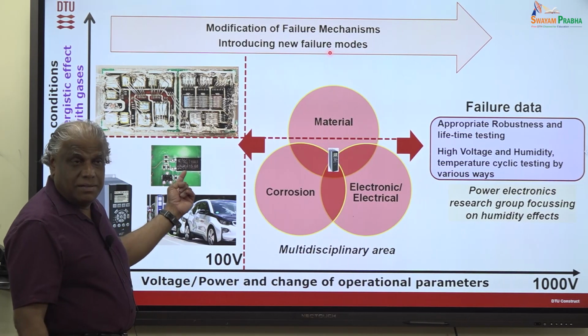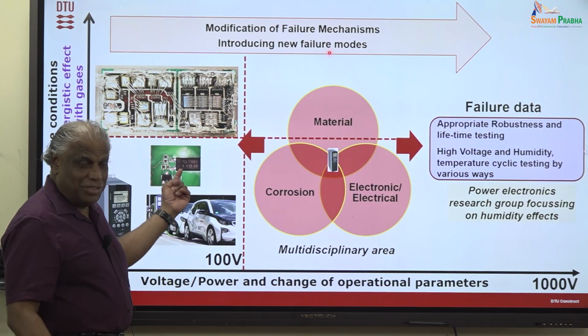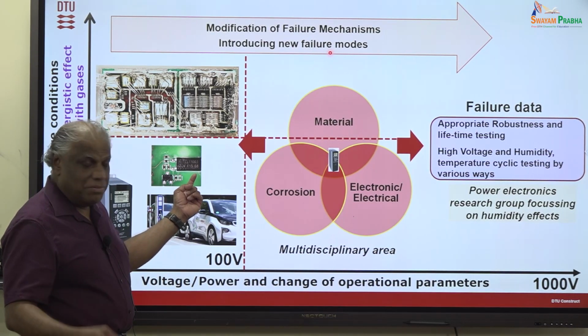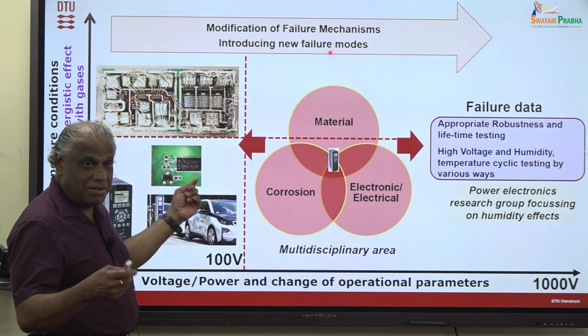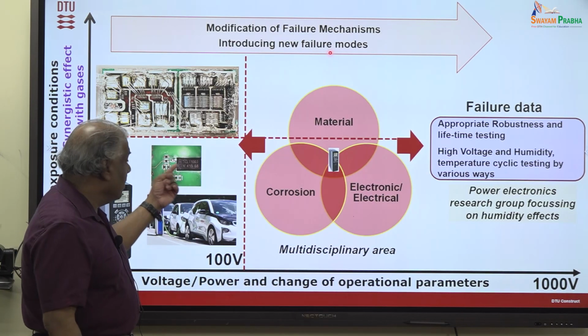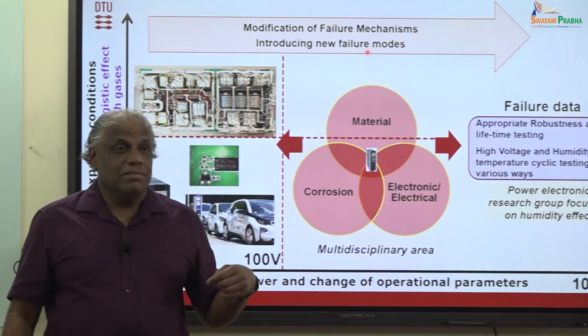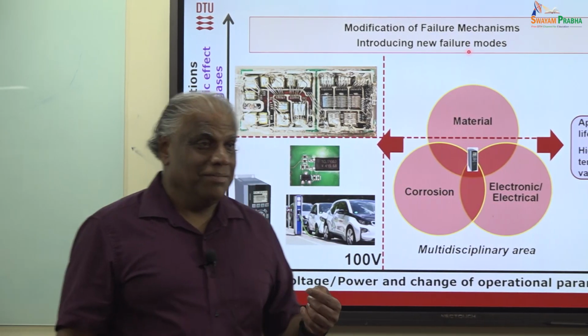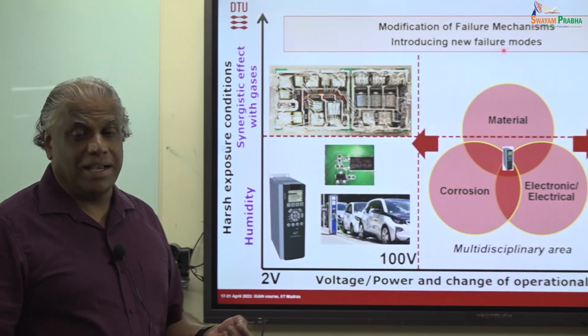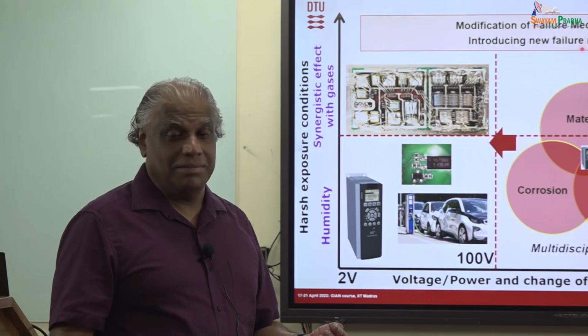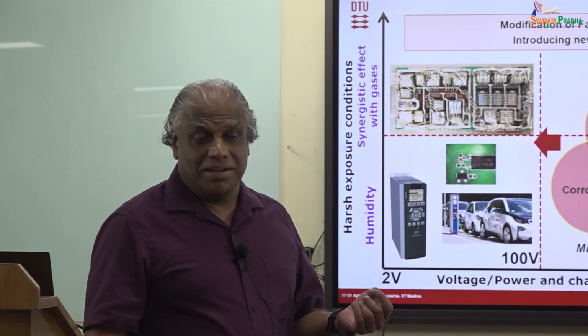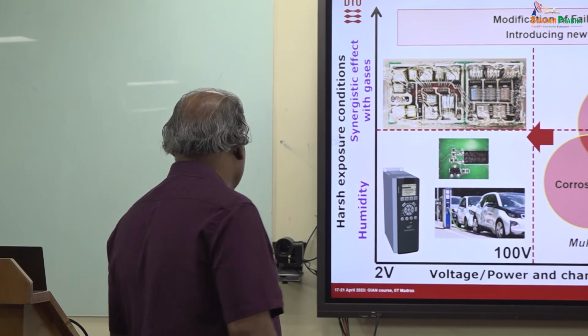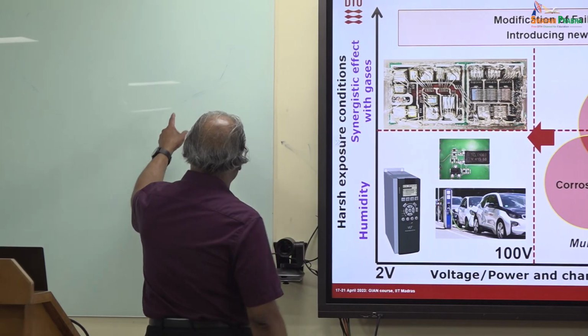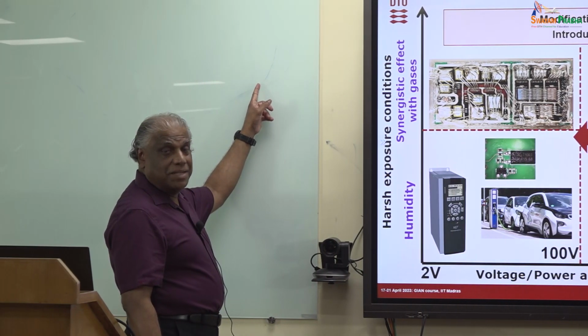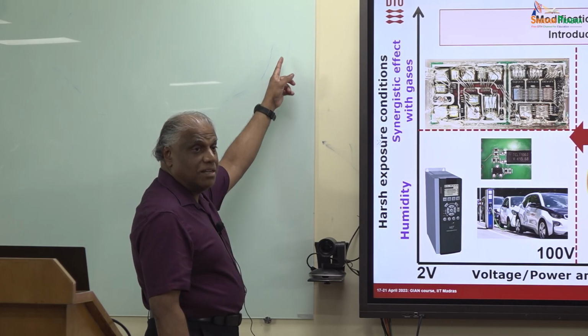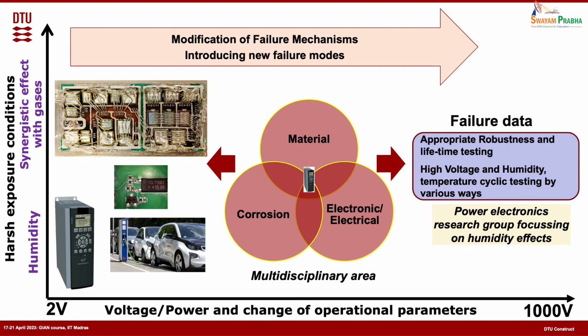thin film of water, which we also have to prove and do a lot of things to make sure that this is the case. When you have a thin film of water, there's no point in increasing the voltage, because even if you increase the voltage, you come to a stage where you cannot pass more current through the solution, right? Yesterday we were discussing, I don't know which group, drawing this polarization curve. When you keep increasing the potential, depending on the conductivity of the solution, at one point you start seeing this resistance limit.